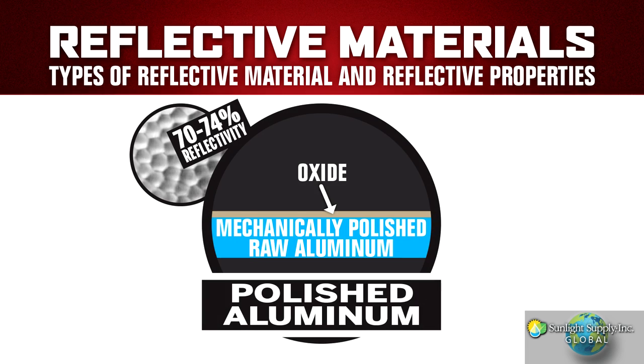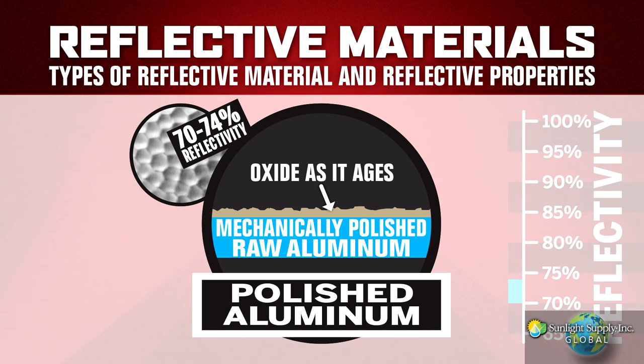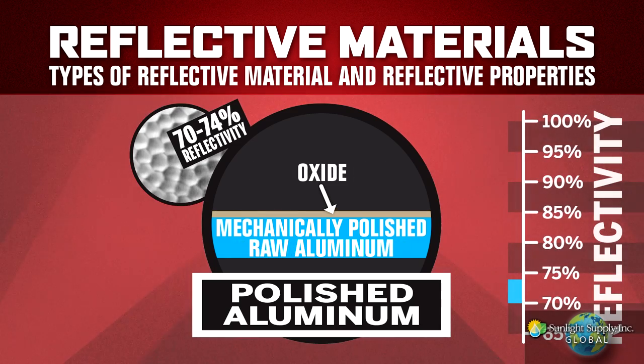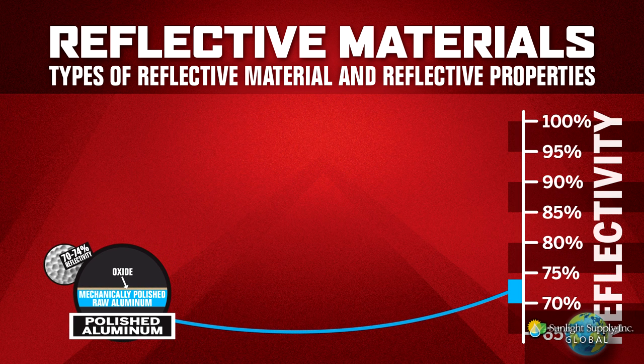The lowest grade is a base aluminum that is mechanically polished and allowed to naturally oxidize, which occurs when non-treated aluminum is exposed to the oxygen in the air. This is referred to as the passivation layer, or native oxide. Heating and cooling of this raw material is a catalyst for further oxidation, which occurs when the lamp is operated and then shut down. This results in an uneven thickness of the oxide layer as it changes over time. This naturally occurring, unstoppable process greatly affects the reflective properties of the material, especially in the lower UVA wavelengths, which can be critical to the plant's growth response. The oxidized alumina typically measures total light reflectance in the very low 70-74% range. We do not use this material in any of our hoods, but this low-grade product is most often found in cheap Chinese-produced reflectors.